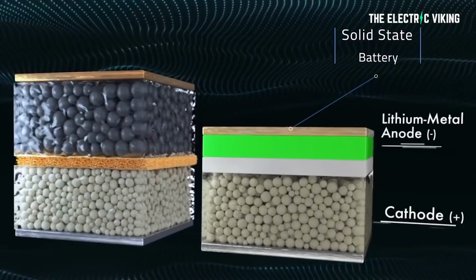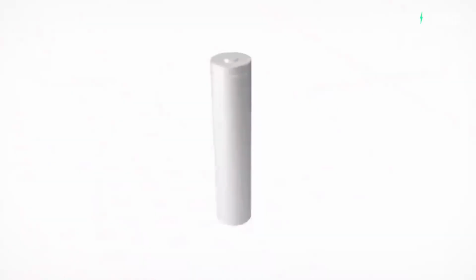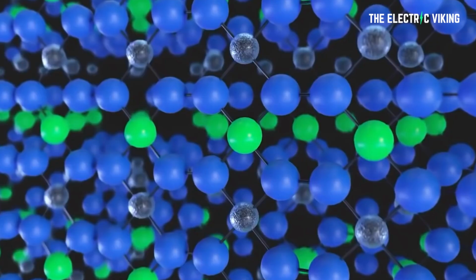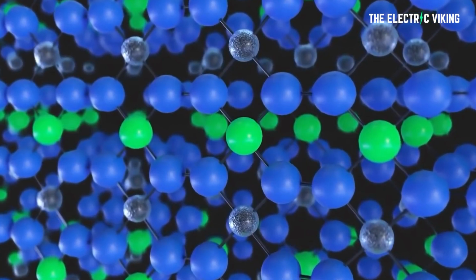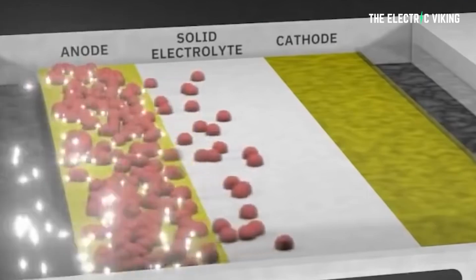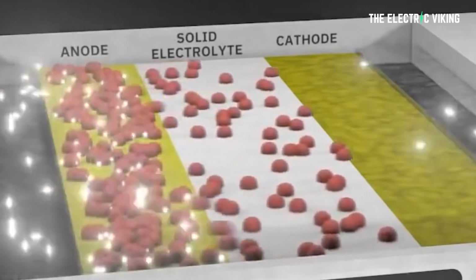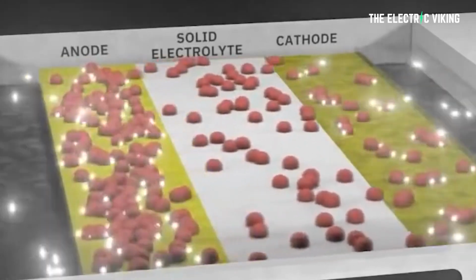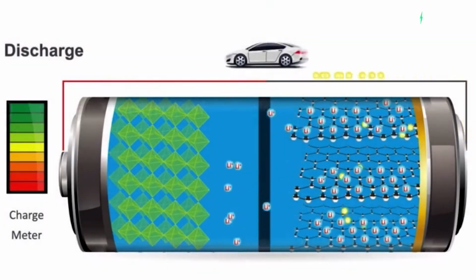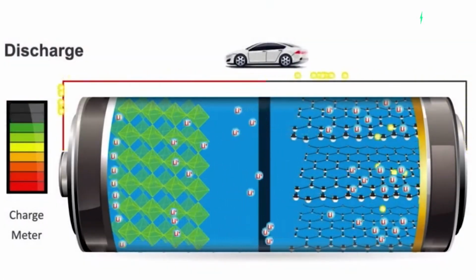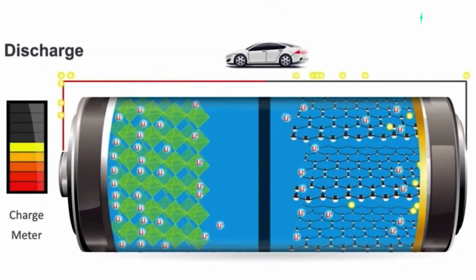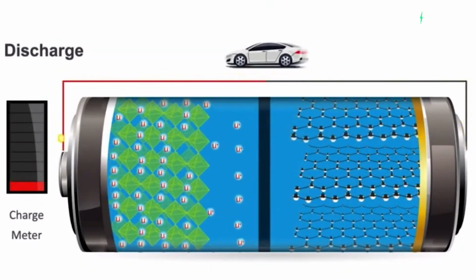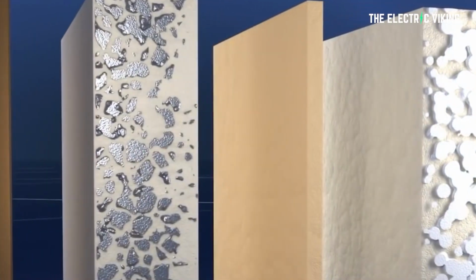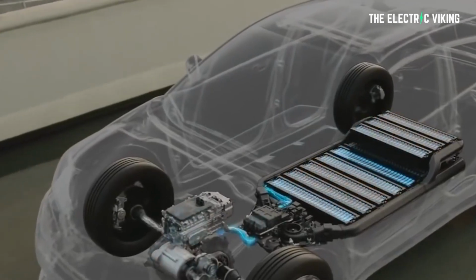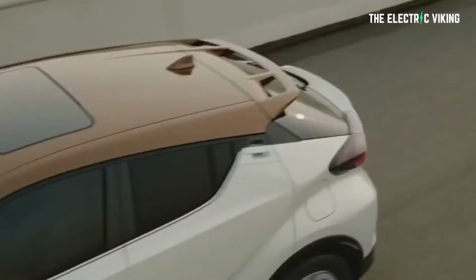The team found that the THNS-based anode showed a high discharge capacity of 380 milliamp hours per gram with a current density of just 0.025 amps per gram, and there was potential that a discharge capacity of 174 milliamp hours per gram could be achieved for a high current density of 1 amp per gram with a 10-minute charge time and a capacity retention of 89.7% after 1,000 cycles.